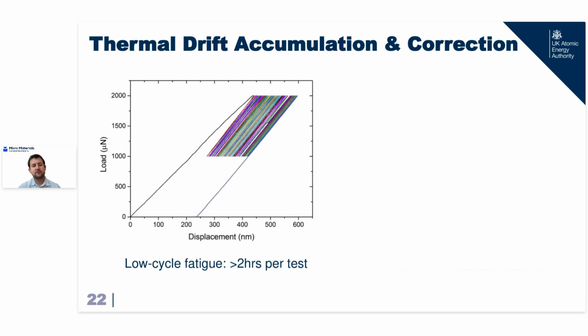Now, when you take these tests up to high temperature, especially when you want to take them to very long time scales, where you're looking almost into a low cycle fatigue range, your experiment time gets very long, several hours per test. This is a relatively quick one that only took 2 hours. And you can see the raw data implies that we've got about 250 nanometers of permanent deformation.